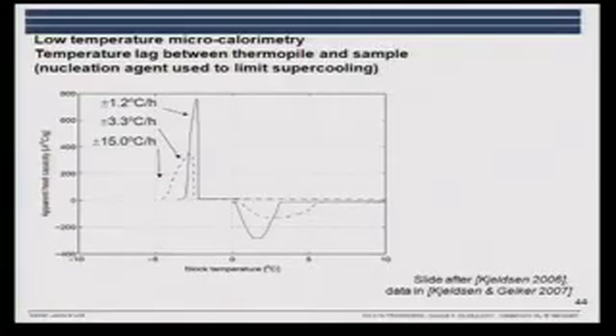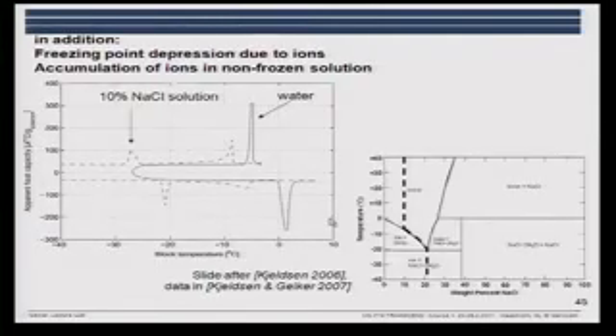Here you have a curve showing the impact of freezing rate on the freezing peak, and this is just water in the calorimeter, and we are freezing at low rates, which gives a distinct peak, whereas if we are freezing at high rate, we have this flat peak, which you can see here. And the same for the thawing curve. If we then add ions, we see a change in the peaks. It's just a very simple system. We wanted to see what was happening.